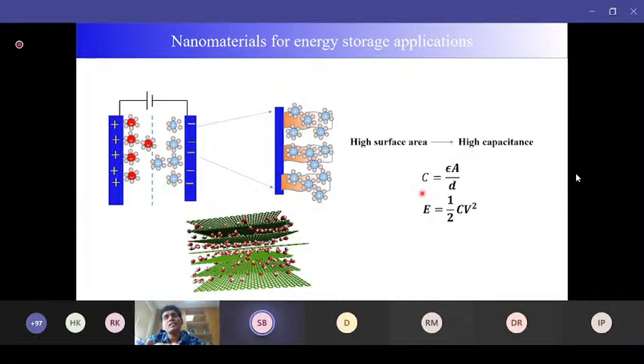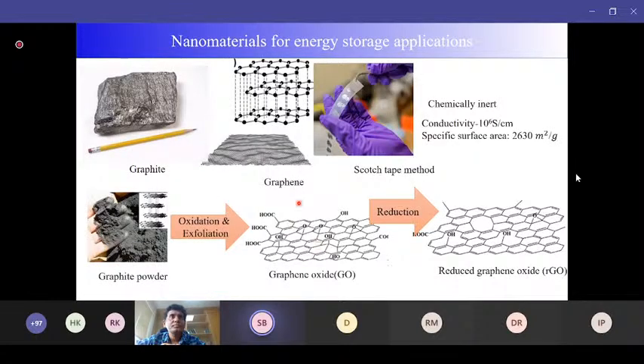Again, I can refer to this formula, C is equal to epsilon A by D. If you can increase the area A, then you can increase the capacitance, and as a result, you can increase the energy density. In this connection, one example I have given over here is some sheets of graphene, which I am going to introduce. Instead of having a solid electrode, if you have several nano sheets of graphene, the electrolyte ions can be stored over each individual surface. As a result, you can increase the energy density to a larger amount.